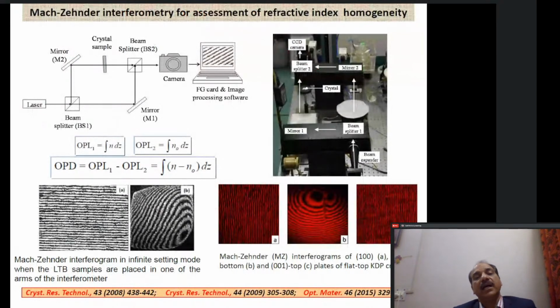Now this is the earlier Mach-Zehnder interferogram which I showed you, used for in situ and online monitoring of the growth process. The same interferometer, if you do not have the growth chamber in the beam path, you can use for ex situ quality assessment of your grown crystal. You put the crystal sample, in the form of a plate, in the beam path, and you will see interferograms like this. So a Mach-Zehnder interferogram in infinite fringe setting mode looks like this.